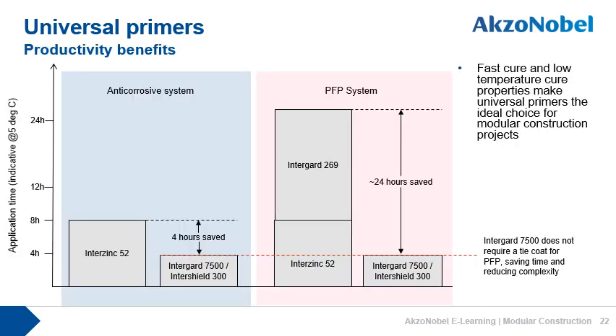In addition to the complexity reduction, which obviously reduces inventory cost and potential for human errors, there is also a massive productivity benefit in moving to this universal approach. As you can see on the graphic in this slide, using Intershield 300 or Intergard 7500 can save huge amounts of time in the paint shop, which is often a bottleneck in the project. As shown here, Intergard 7500 or Intershield 300 can be overcoated in just 4 hours compared to a typical zinc-rich epoxy that takes 8 hours at an ambient temperature of 5 degrees C. And that means you can get through 2 coats in a shift with the universal primer rather than just one if you're using a zinc-rich primer.